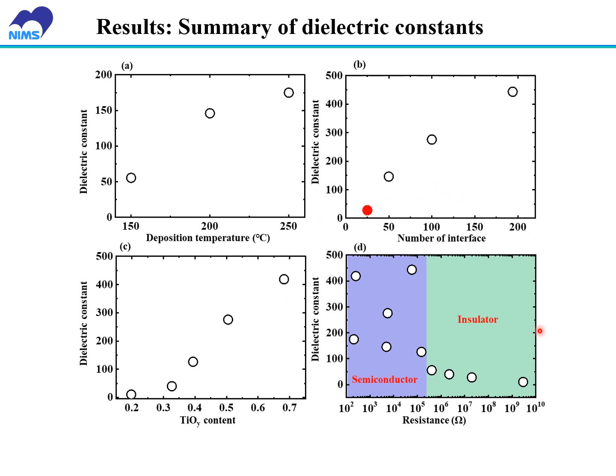Based on the IV characteristics, we can also obtain the resistance of the ATO nanolaminates. When the ATO nanolaminates are semiconductors, their dielectric constant is higher than 100. In other words, they are higher than those of the single titanium oxides. However, when the ATO nanolaminate is an insulator, its dielectric constant is lower than 100.